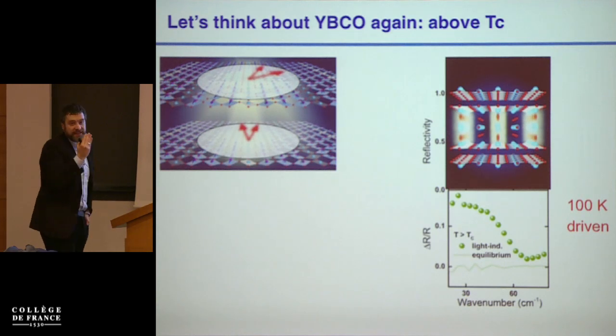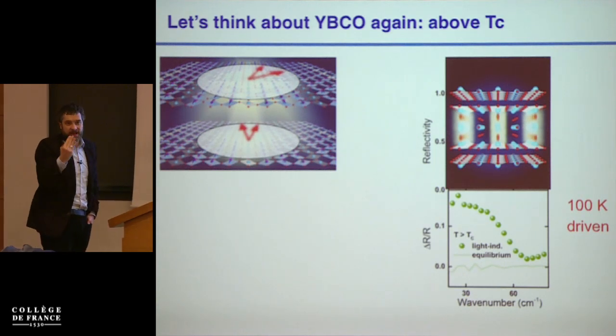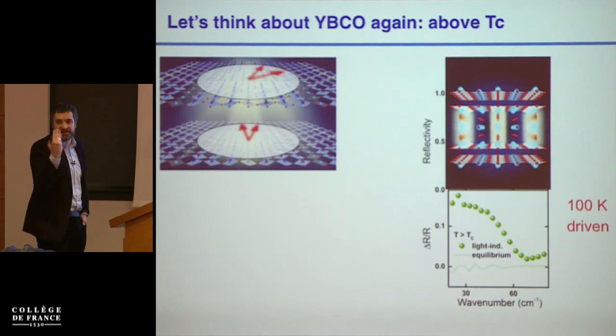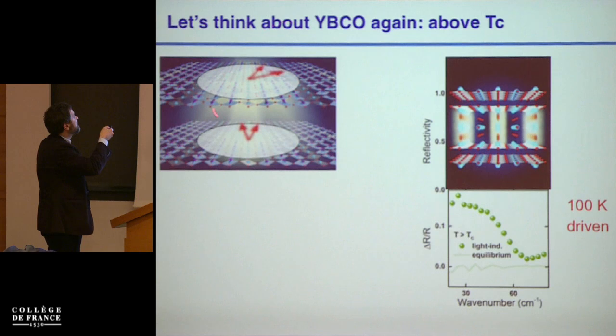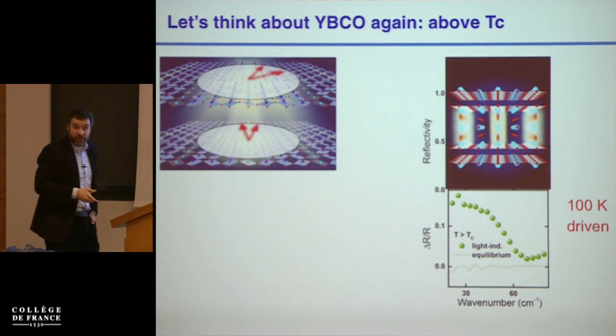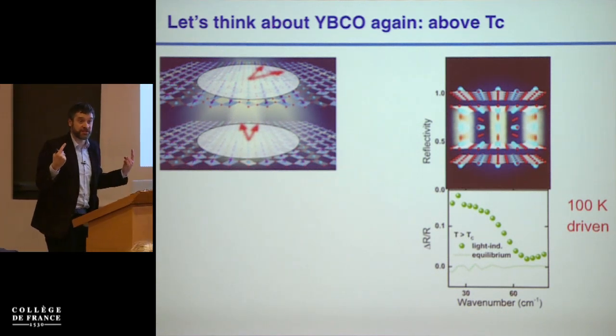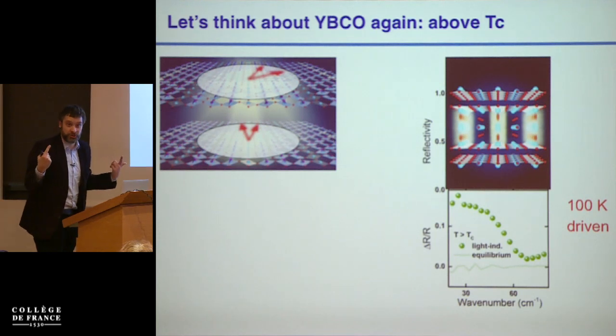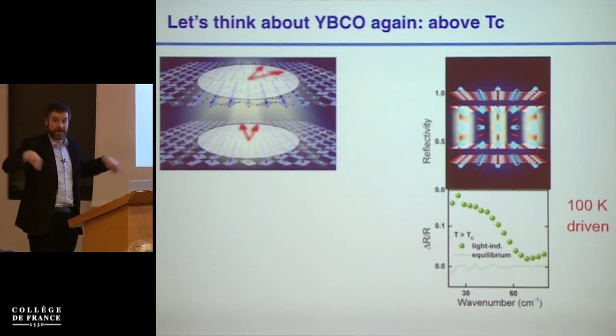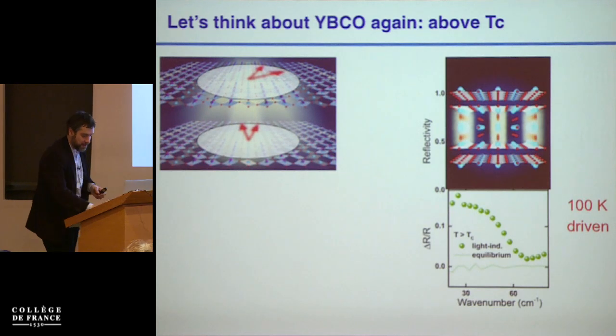So let's think about this effect, and let's assume that above Tc, I retain some finite pairing amplitude, and the reason why the system is not a good superconductor is that this phase is going around and the 2 phases are uncorrelated. So let's do the same game with the Kapitsa pendulum that I showed you before. Imagine 2 pendula that are rotating and start modulating one.